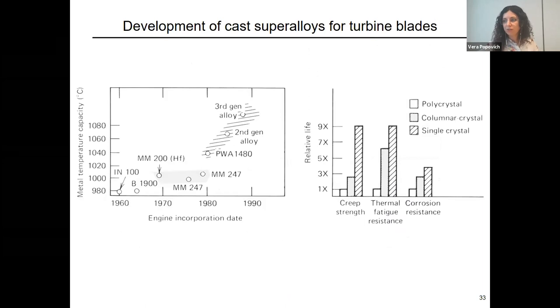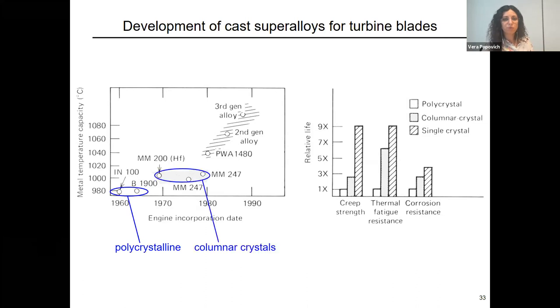To give a more visual picture, the implication of improving or changing the grains is given here. We see that the surface temperature, so the melt or the temperature capacity, increases with increasing alloy generation, but also going from polycrystalline to columnar crystal to single crystal. And this is an example of polycrystal, columnar, single crystal. For sure this has a very direct implication for the lifetime. You see the relative lifetime: creep strength, thermal fatigue, and corrosion resistance. It's really undoubted how much, by an order of magnitude, so 3 times improvement for columnar crystals and almost 9 times improvement for a single crystal.